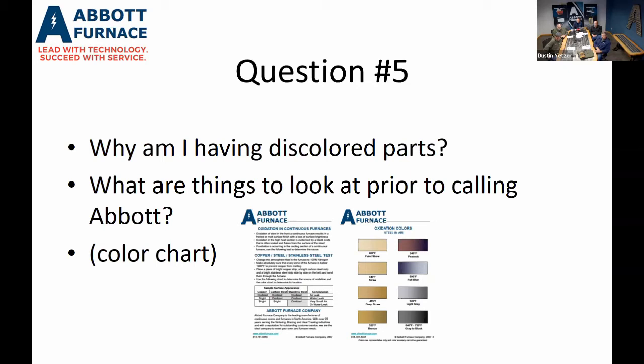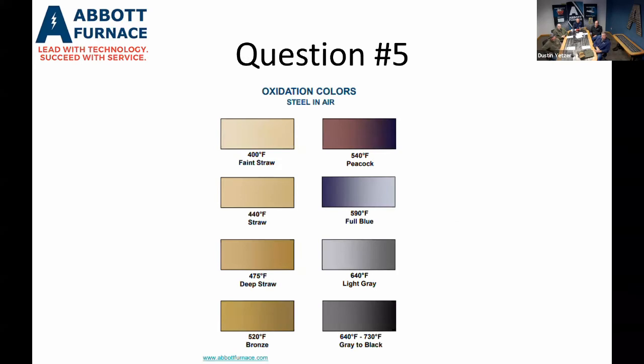back of the furnace, what we see a lot is, as Brian touched on, people's curtains are damaged or lowered too little. They're getting air up through the back. Maybe sprung a leak in one of your lines. I mean, it just depends on what color you have on your parts and where you're at, I guess is how I can put that. And as Brian touched on earlier about the seasonal, we do see that a lot up here in Pennsylvania. That's a lot of it. But the main cause that'll do that is your curtains coming up back. You are getting air up through the back of that furnace, and you've got to try to get a balanced flow to help the atmosphere get back there to keep the air from coming up through the back. Okay, thanks, Matt.